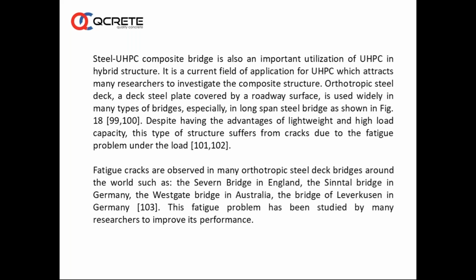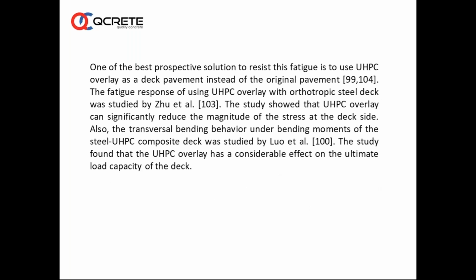The fatigue problem has been studied by many researchers to improve the performance. One of the best prospective solutions to restrict this fatigue is to use UHPC overlay as a deck pavement instead of the original pavement. Fatigue response of using UHPC overlay with orthotropic steel deck was studied by Zhu. The study showed that UHPC overlay can significantly reduce the magnitude of stress at the deck side. Also, the transversal bending behavior under the bending moments of the steel UHPC composite deck was studied by Luo. The study found that the UHPC overlay has a considerable effect on ultimate load capacity of the deck.